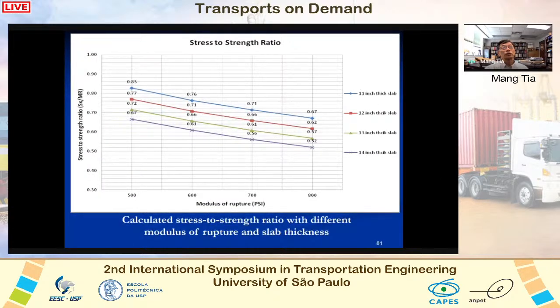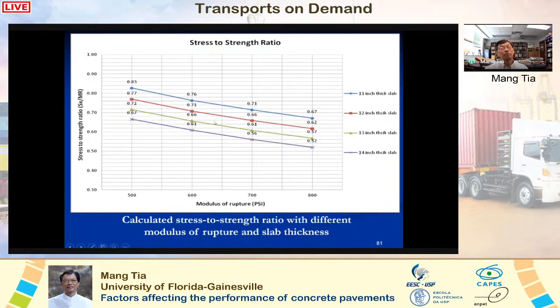These are plots of stress to strength ratio as a function of modulus of rupture and slab thickness. Concrete made with the best aggregate among the three. Okay, they're not necessarily the absolute best, but among the three, the best aggregate, the Brooksville aggregate, was used in the analysis, and the relationship between the elastic modulus and modulus of rupture of the concrete was used to determine the elastic modulus of the concrete needed in the analysis. So when you assume a certain flexural strength, you have to estimate the elastic modulus of that concrete, and we use the equation that we developed earlier to make those estimations.